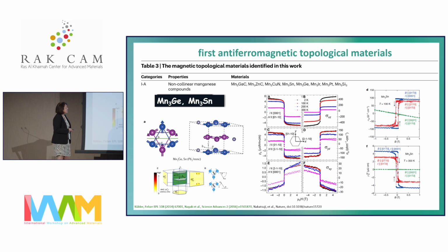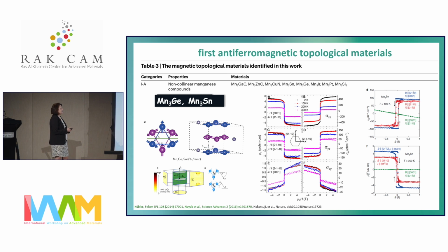And Ajaya Nayak made this compound in my group, and he measured the anomalous Hall effect, and indeed he found an anomalous Hall effect. This is a Hall measurement simply, and you see here a large jump, and this is unexpected for an antiferromagnet. You would expect here simply a linear line, which you find for the Allan MacDonald compound, but not for our compound. And at the same time, Nakatsuji investigated manganese-3 tin, and he found the same, so it was clear it's not an impurity and it's not a mistake. Nowadays, we know that we can find in these topological antiferromagnets unusual behavior, like in ferromagnets. And then you can also look at this compound for the Nernst effect.